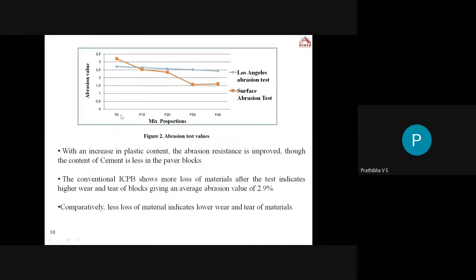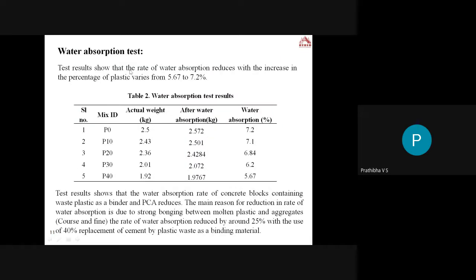Here we can see P0 in the mix proportion, that is the conventional concrete, and P40, that is 40% replacement of cement, incorporated with PCA. The abrasion is very much reduced. We can see the surface abrasion is reduced by around 69% compared to the conventional concrete. So we can say that with the increase in plastic content as a binder, the blocks offer more resistance to abrasion. So the last test is the water absorption test.